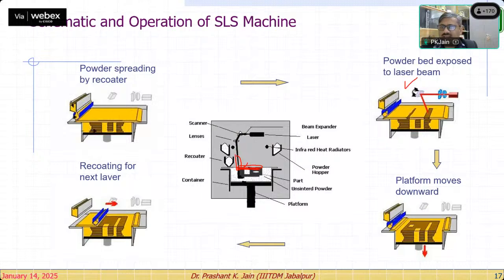This laser beam will come on the selected areas only, like you see in this figure. This is the recoater, so it recoats the powder. This layer thickness is around 150 micron. With just one layer recoated and reheated, it reaches around 172 degrees centigrade. The remaining 4-5 degrees centigrade temperature rise occurs because of the laser beam. So only in the selected area the laser beam occurs and the part solidifies.